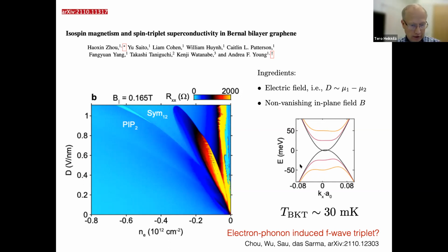To make the story short, they find superconductivity once they go to these edge states. And actually, das Sarma also there used a similar approach as ours to show that the electron-phonon coupling can also explain these experiments. The curious thing about these experiments was the fact that the superconducting state, which is actually here, only shows up at finite in-plane magnetic fields. At zero field, it doesn't show up.